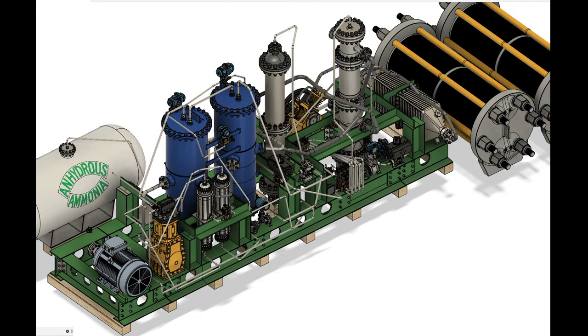The Tesoro-Anacortes refinery explosion in 2010 was caused by high-temperature hydrogen attack weakening the heat exchanger wall housing steel, causing it to rupture. To this date, ammonia converters failing in a catastrophic manner imputable to hydrogen attack has been documented only once, while for nitriding-induced embrittlement, no case has been documented. This illustrates the success of materials selection and the safety factors employed in choosing the appropriate wall thickness, despite the immensely harsh and antagonistic conditions experienced during ammonia synthesis.